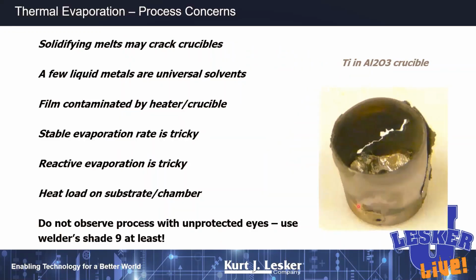Now, if you're using crucibles, those are probably going to give you a little bit more life, but just know, again, this is titanium in an aluminum oxide crucible, that after heating for a while, if the titanium happens to wet to the ceramic, after you cycle it a few times, you're going to have maybe some cracking. The coefficient of thermal expansion between the titanium and the aluminum oxide is such that it's going to eventually stress that boat out, or that crucible out, and you're going to crack it. Once you crack it, you're going to have molten titanium running around your vacuum system, and that's considered bad. So don't do that. Keep an eye on your crucibles, so you don't crack them or put holes in them and leak molten metal all over your system.